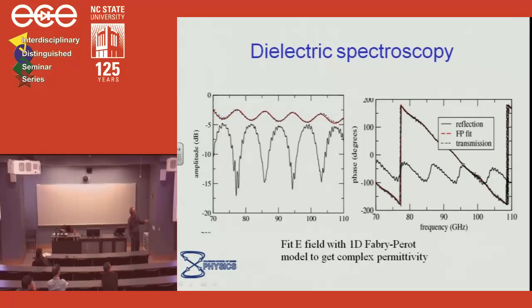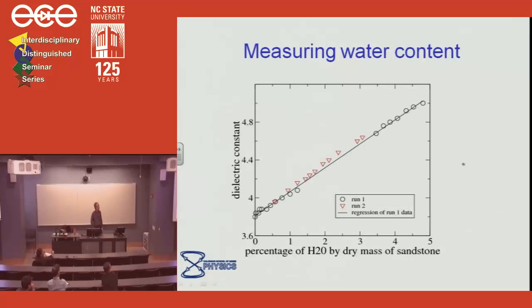So you do this fit, a least squares fit, and you get the real and imaginary part of the dielectric constant, just like that. It's very fast. And so you can do things like watch the paint dry. In this case, watch a rock dry by measuring the dielectric constant of the rock as it just sits on the bench in the lab. We have very low humidity in Colorado, and just watch it dry out. So in this case, you can see this nice linear trend of dielectric constant as the water evaporates.